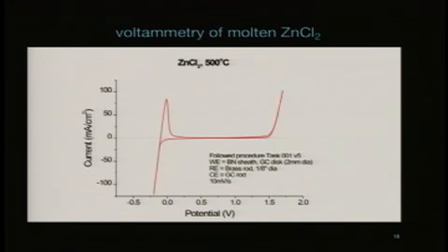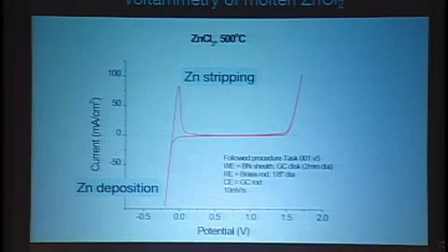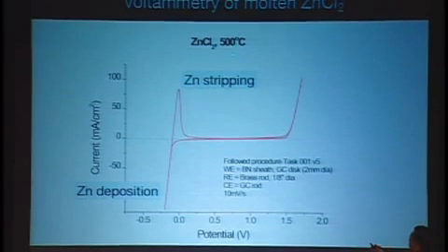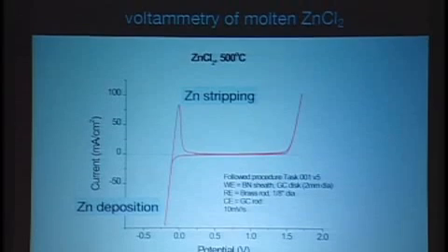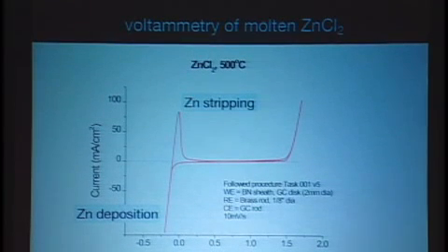So here's some basic science just to show that we don't just play with liquid metals and blow bubbles and so on. This is a current voltage characteristic. We're measuring the current as a function of potential. What happens with zinc chloride as a supporting electrolyte? If we go to very cathodic values, we see a peak associated with zinc deposition. We start sweeping back. This is the stripping of the liquid zinc that has just been produced. Temperature here is 500 degrees C. Zinc melts at 420. And if we go to the other extreme, we get chlorine evolution.